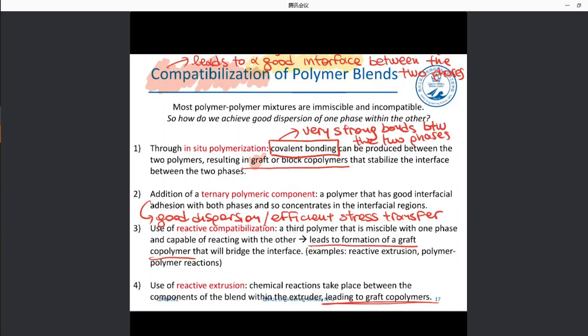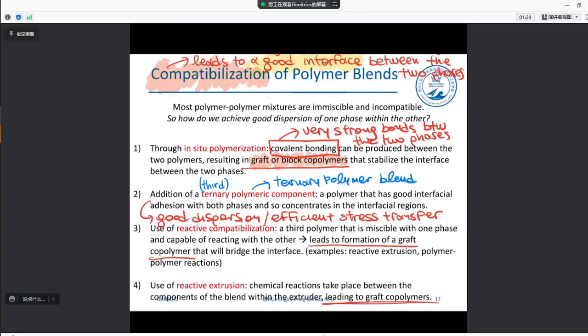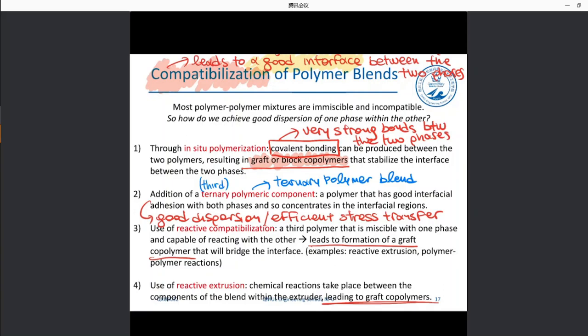We will see in a bit how these block copolymers stabilize the interface. Usually we can add a third component. Ternary means a third. It's a fancy word for a third polymeric component, a polymer that has good adhesion with both phases. If we disperse it very well, we obtain a ternary polymer blend, which, because of the good interface and the strong bonding between the phases, now has efficient stress transfer under mechanical stress.